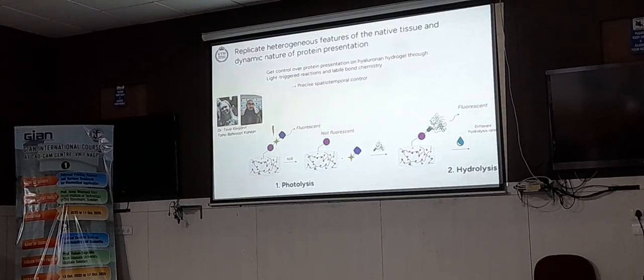creating this part where we have the growth factor covalently bound to the hydrogel. And then since we have a bond here that can be broken by hydrolysis, and that they have different stability, it would release at different time points using hydrolysis.